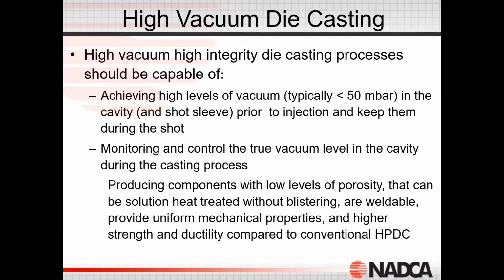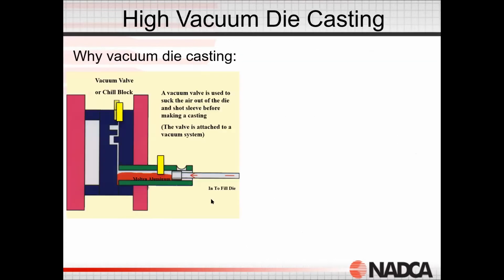So with that better elongation, their durability in crash tests, in bending instead of breaking and snapping. So we're reaching elongation values of 10 to 12, 15% in some cases. So with that high elongation, we're going to deform the casting and not break the casting in a crash test situation. So why use vacuum die casting?